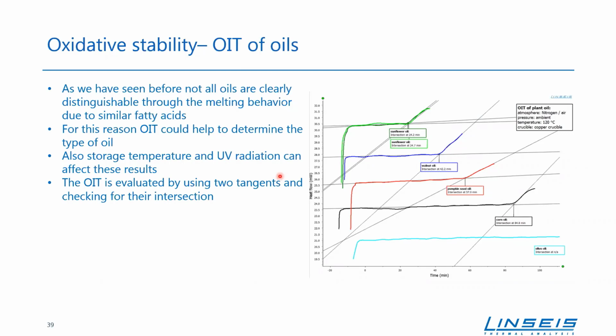But what we also can see there is sometimes no result or no effect is also a good effect. For example, olive oil doesn't react under these ambient conditions in this time at this temperature. So this is what we want to prove. OIT could help to determine the type of oil, for example, if there's no clear separation through the melting behavior at all. But what's of course also important is the storage temperature and storage conditions, as well as the UV radiation, because they will also affect the results.